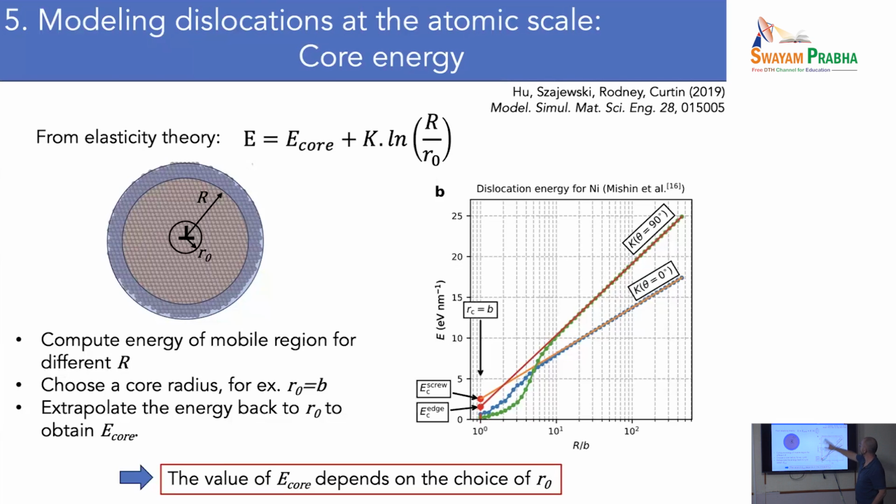And then for different dislocations, so you see here it's in nickel, so it's an FCC metal, and it's modeled with the Mishin potential. I showed the paper yesterday, so you see something very classical. And this is the energy inside the cylinder. We don't want to compute the energy of the outer atoms because this would be influenced by the surface. So we compute only the energy inside. So this is the energy as a function of the radius, of the log of the radius.